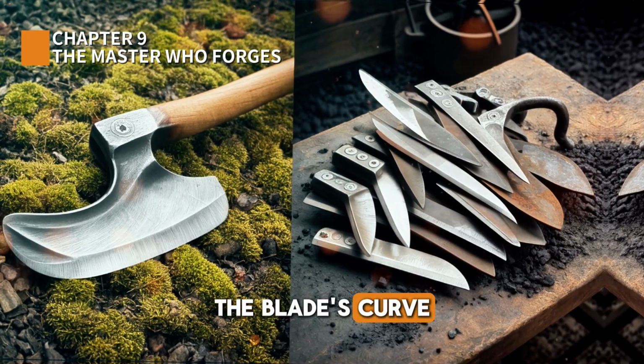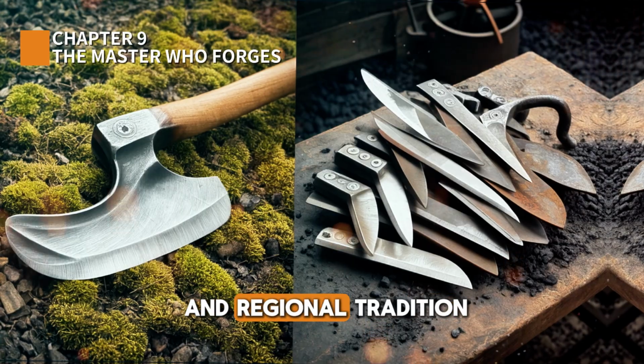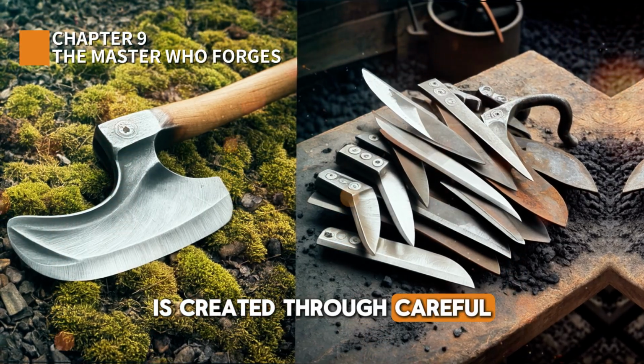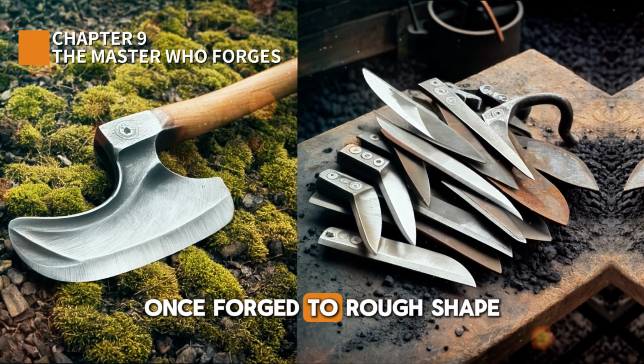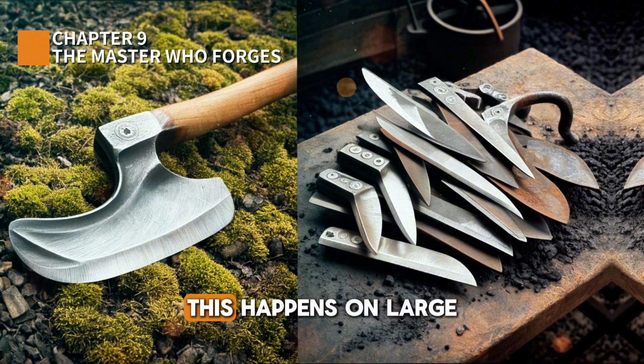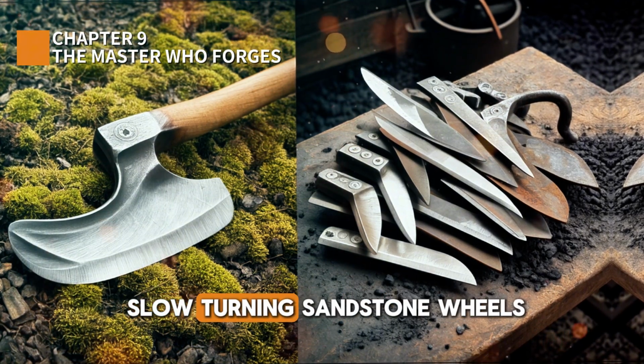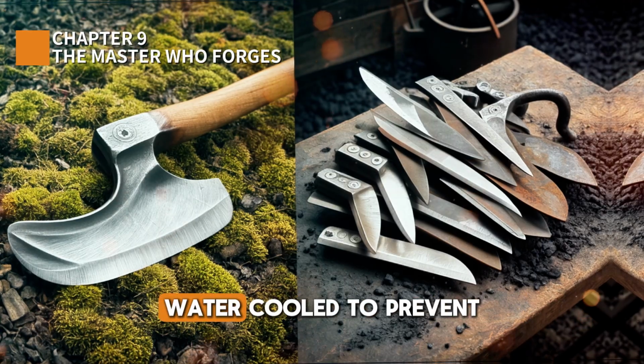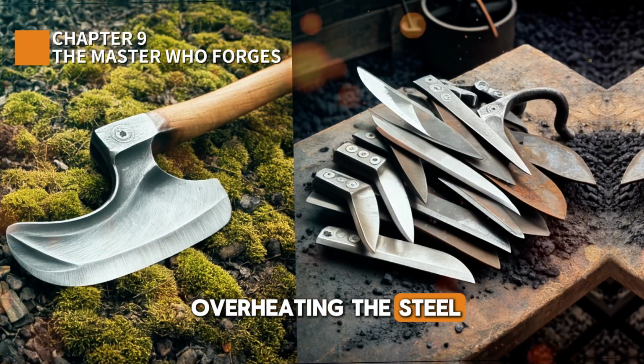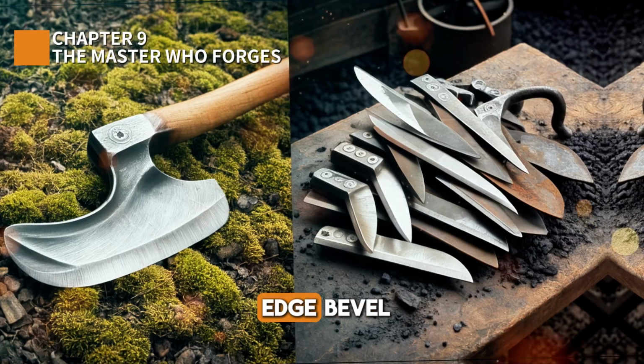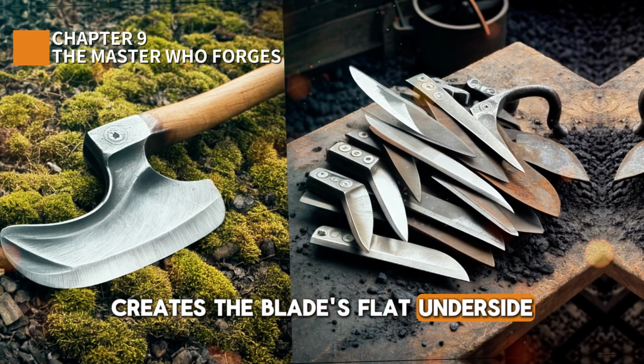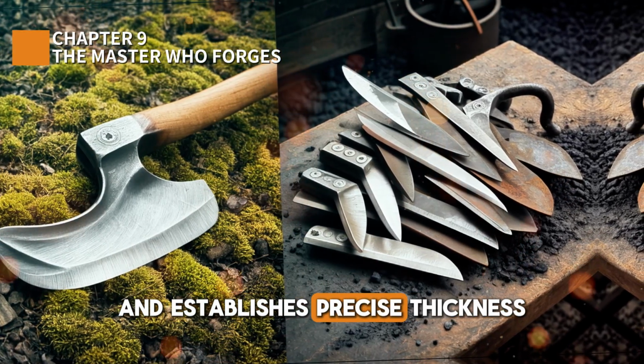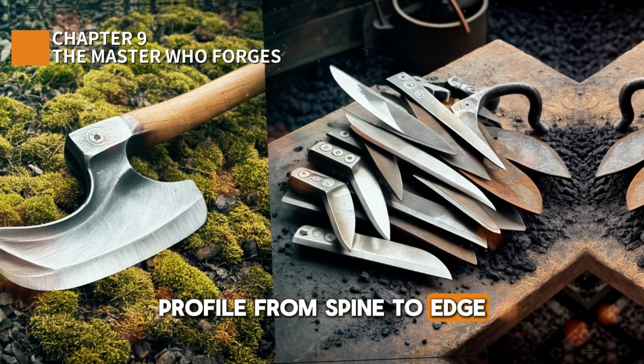The blade's curve, specific to scythe type and regional tradition, is created through careful hammer control. Once forged to rough shape, the blade is ground. This happens on large, slow-turning sandstone wheels, water-cooled to prevent overheating the steel. The grinder shapes the edge bevel, creates the blade's flat underside, and establishes precise thickness profile from spine to edge.